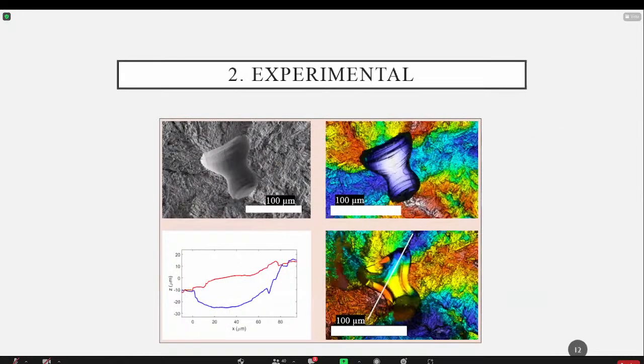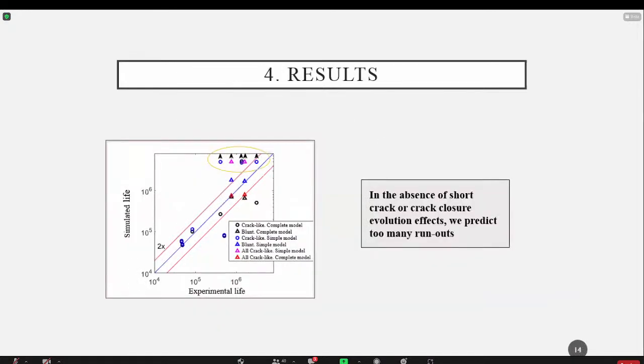This is clearly a blunt defect. So we applied the model to both situations, and the model is composed of two different parts. For those defects that were considered crack-like, that were very sharp, we didn't consider the initiation. We considered that this defect would behave as the initial crack, and it would start propagating right away. But in the blunt defects, we did include this initiation. But we came to the conclusion after all the simulations, I can show you here.